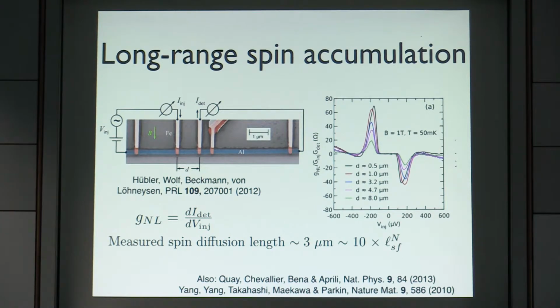And the decay scale of the signal that was obtained from these distance-dependent measurements could be inferred to be several micrometers. Okay, and this was a kind of a mystery at that point, because basically it was 10 times larger than the spin flip relaxation length in the normal state. Similar kinds of experiments were done by Marco Aprili's group, 2013, with quite similar results. Well, there was also another experiment by Stuart Parkin measuring actually longer spin relaxation times in these experiments.